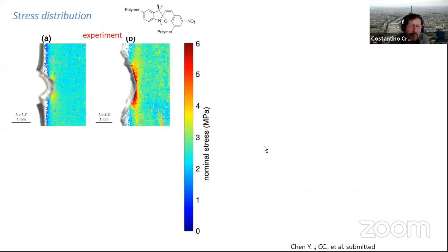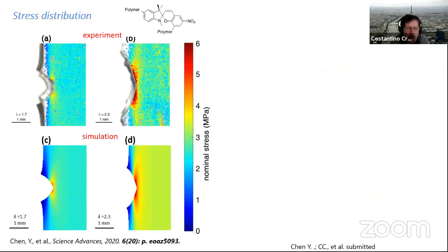This is the experiments for two different materials, very close to fracture, using the same stress map, because we're using the same probe in this case. And if you look at the finite element simulation, which is slightly tilted, just like the sample, you can see that the agreement here is actually pretty good, knowing that there is no adjustable parameter in the simulation. So the simulation is taken directly from the calibration, and we're just stretching on it. And here you're calculating the stress. So this is the calculation based on the material model. And this is the actual measurement.